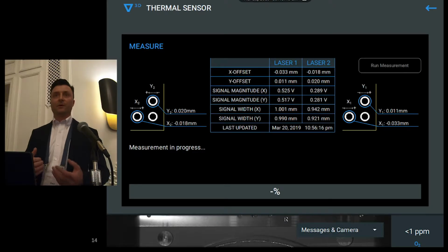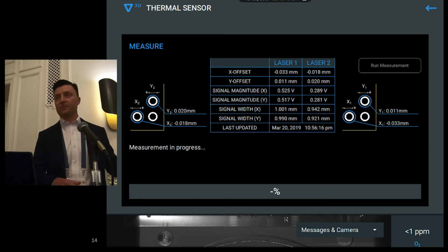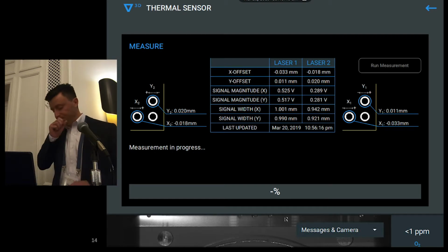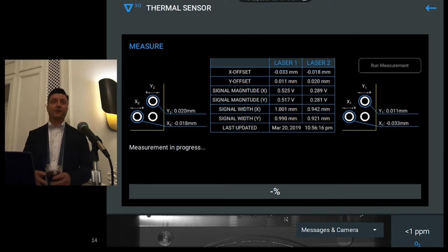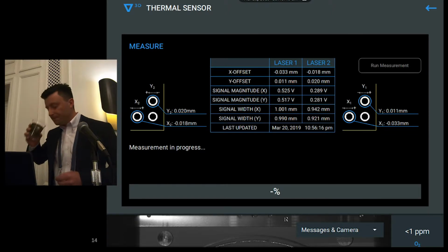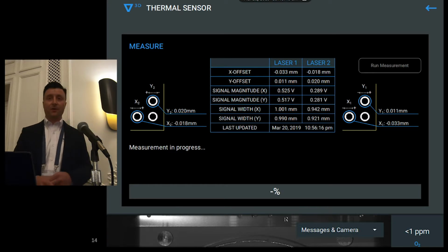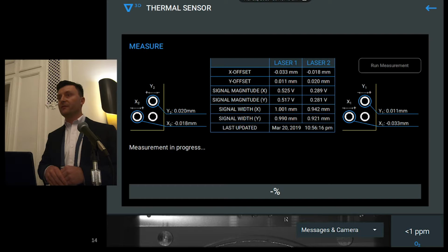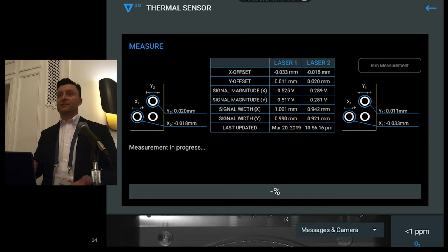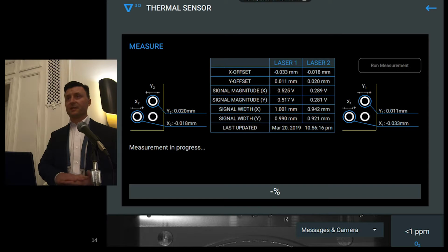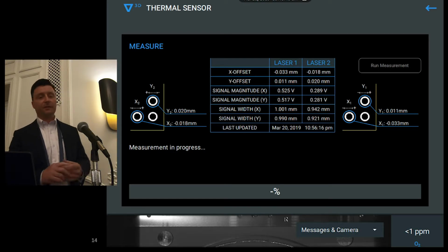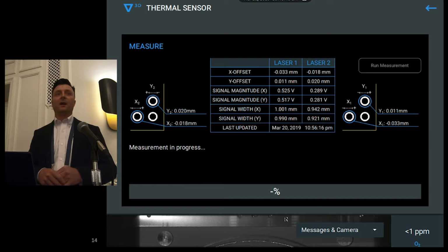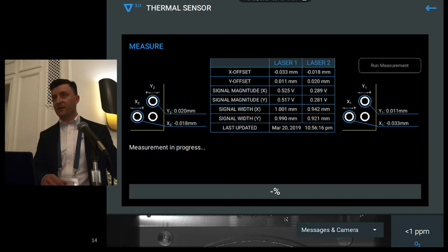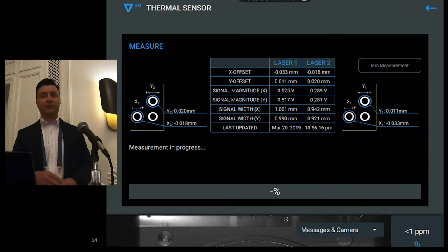And all this is well and good as long as you trust your sensors. And that's a really big part of this. You can't do closed loop control, you can't do these laser measurements and calibrations in situ unless you have a really robust sensor and it's characterized. So the system also can make sure that the sensor that you're using to do all these measurements is essentially self-calibrated. So we can make sure that it's aligned with what it needs to be aligned with, and that your intensity is good, that your signal width is good, and that you can trust the output of the sensor. So that's kind of a critical part of this that you want to also be tracking in time.